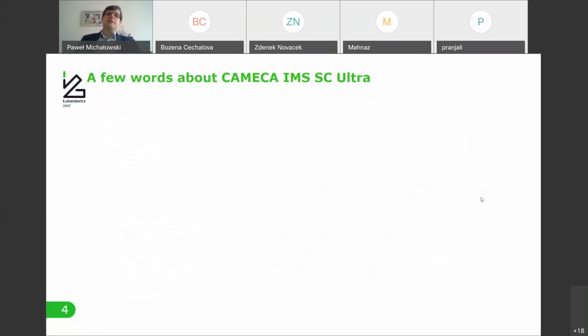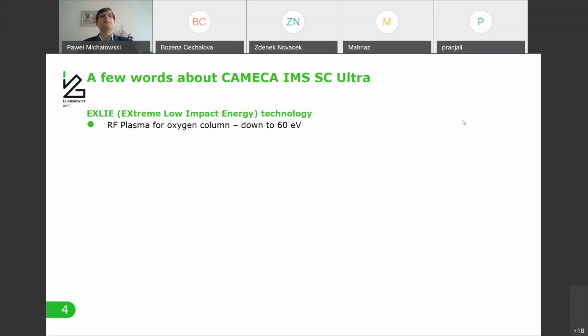Okay. Now I would like to talk a little bit about the instrument that I use, about its main differences when compared to most of the other spectrometers. So the first difference is the so-called extreme low impact energy technology. While probably you know, in most cases, the impact energy can be decreased to like half a kiloelectronvolt, maybe a quarter of a kiloelectronvolt. In this case, the oxygen gun is not a duoplasmatron, which is commonly used for gaseous sources. But here there is a radio frequency plasma generator, and it can decrease the impact energy of oxygen ions down to 60 eV. While in case of the cesium column, there is an additional floating voltage.